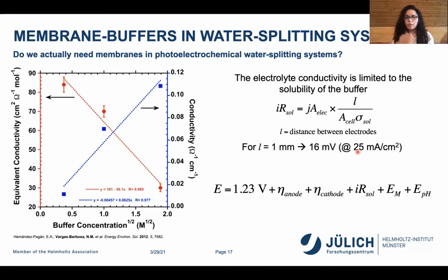And if we look at all of the other losses associated with a water splitting system, we have the thermodynamics of 1.23 volts, the anode and cathode potentials, the solution resistivity losses, those of the membrane, if we are actually requiring a membrane, and then additional pH gradients, okay? And the reality is that in order to make these buffered systems work, we need to keep all of these additional overpotentials below 700 millivolts. Otherwise, we're not competing with alkaline electrolysis. It's just not there.